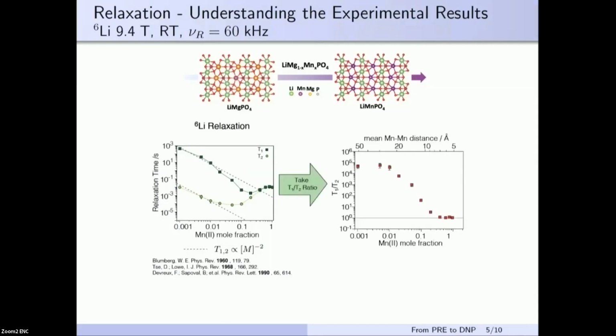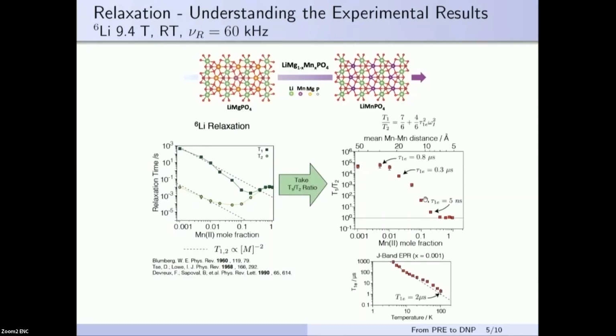If we look now at the ratio of T1 over T2, we get this figure here. At the low concentration, the ratio is largest and more or less constant for a while, and then it starts dropping quickly. Using the equation that I just showed you, we can estimate the electron relaxation time. For the longest cases, we are somewhere around 0.8 microseconds, and then we drop quickly into the nanosecond regime, until we reach the extreme narrowing regime.